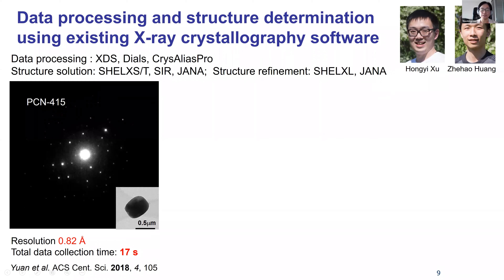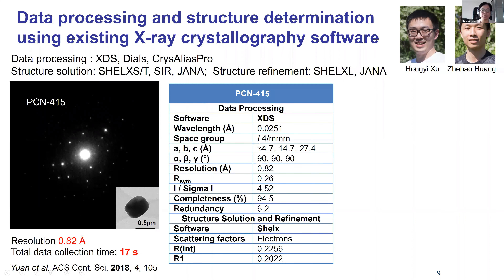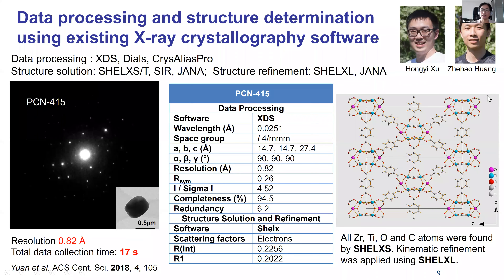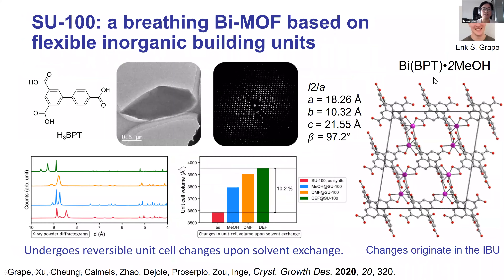Because data collection is almost identical to what is done in X-ray diffraction, all existing software developed for X-ray crystallography can be used — for example XDS, DIALS, and CrysAlisPro for data processing, and standard software for structure determination. We apply kinematical refinement using SHELXL. Everything except the data collection is the same as for single crystal X-ray diffraction, so most of you working in this area will be familiar with the technique.